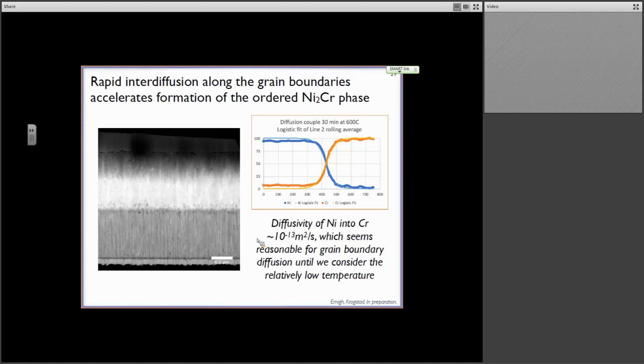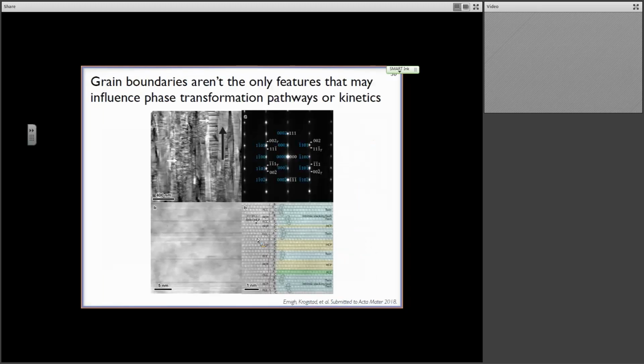Okay? So now we can actually utilize and capitalize on these fast diffusion pathways to study things like sluggish diffusion or sluggish phase transformations that otherwise we don't have the patience necessarily to study in depth, but are really critical to certain applications like a nuclear reactor that's operating for 80 years around 300 degrees Celsius. We can't actually validate that for 80 years. So it can be very difficult to predict what's happening after such a long time period unless you're actually pulling components out of the reactor.